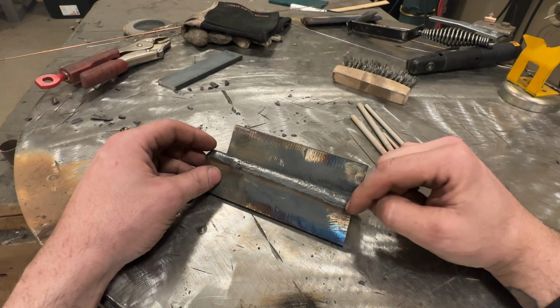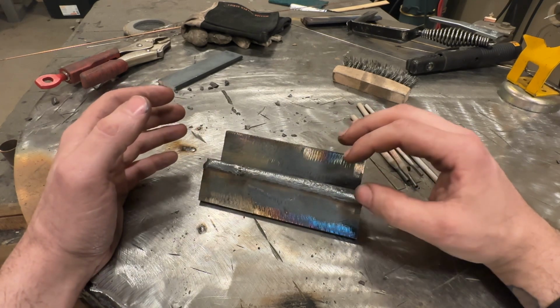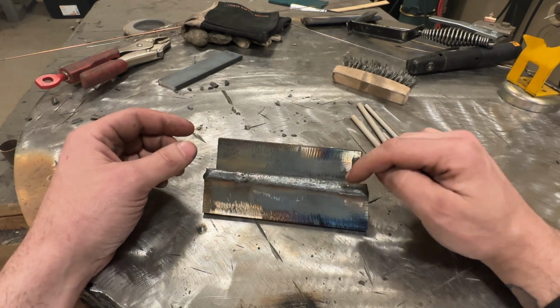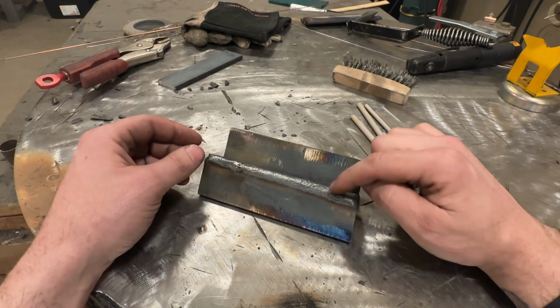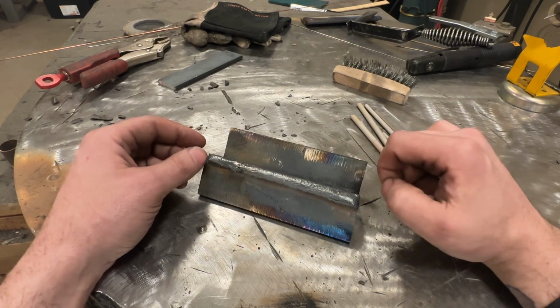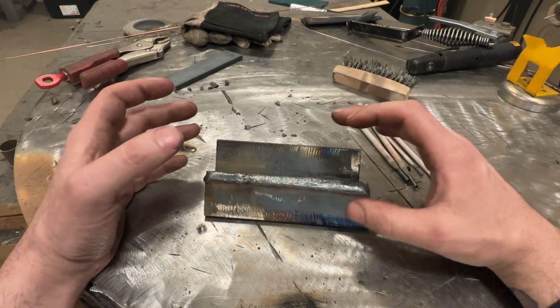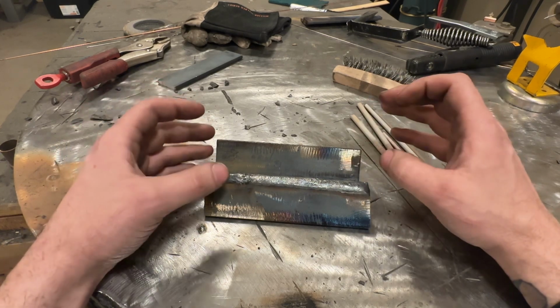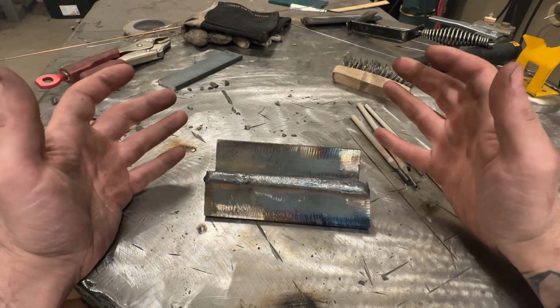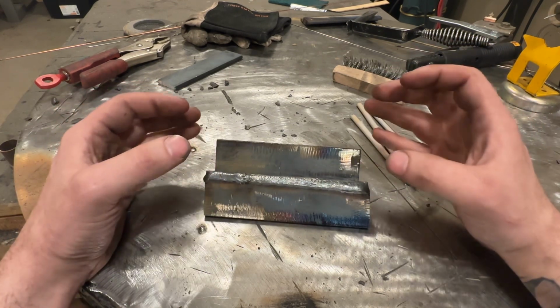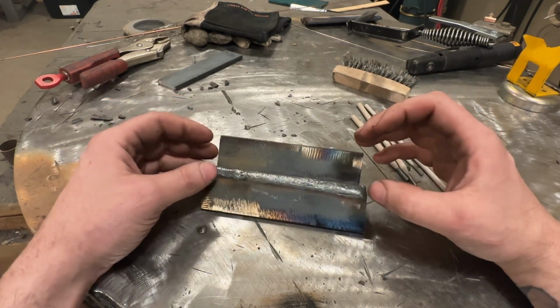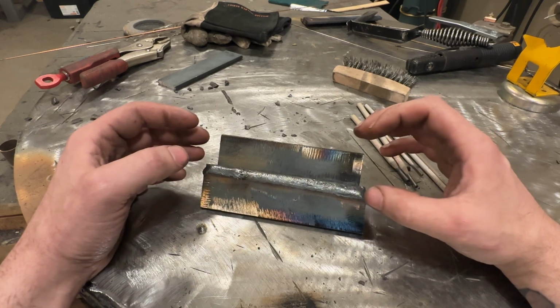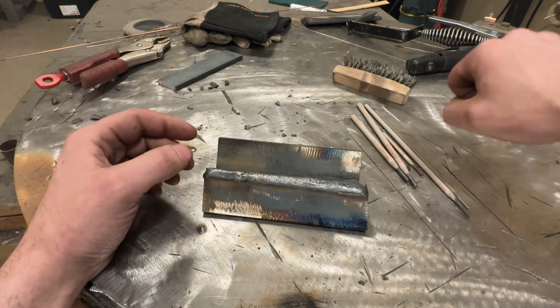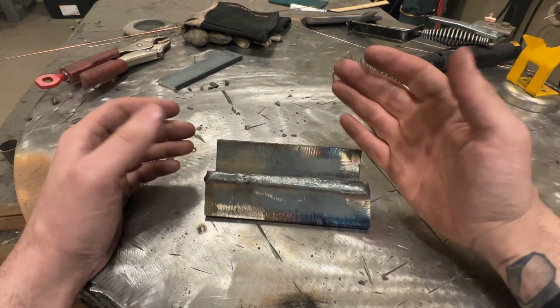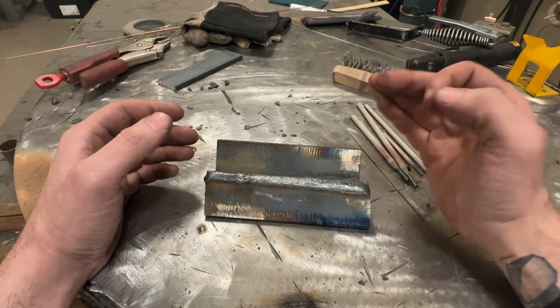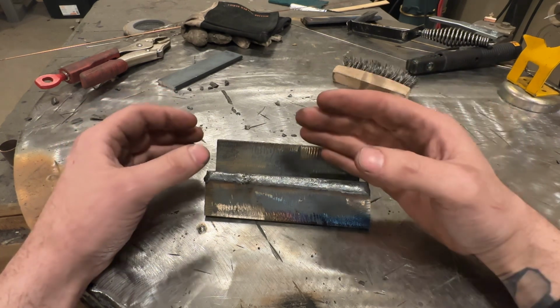Now, 170 amps on this plate was in the ballpark of what was right for it. However, I'm willing to bet if we were to actually do a microscopic examination of this, that the grain structure of this is likely a little bit poorer than the pass we did with the 3/32 1/8. And it has to do with the amount of metal you're depositing. Generally speaking, the more metal, the worse the grain structure is. And that is for a single pass. And that is why it's very common to do multi-pass welds, not only to get to the proper thickness that you want of weld for the material, but so that you're not depositing one big thick, like you're taking a ladle in a forge and pouring just molten metal down in a groove. Like, you don't want that. So layering it produces individual beads that are of higher strength combined than one single pass.